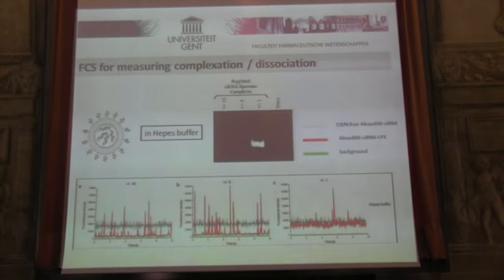Validation experiment. So typically, how would you measure complexation of siRNA into a nanocarrier? Typically we do this by gel electrophoresis. So what we did is we complexed siRNA with pegylated liposomes on a 1:1 charge ratio, a 5:1 charge ratio, and a 10:1 charge ratio, so increasing number of liposomes. 1:1 shows you that it's insufficient complexation, but starting from 5 it should be okay.